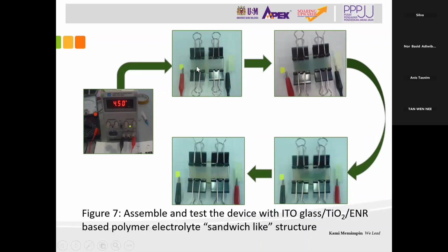This is a demonstration of an electrochromic device showing the polymer electrolyte in the operating mode. You can see here the device changes from transparent to dark blue color. The device is applied with a low voltage of 4.5 volts, and this process takes about 1 to 2 minutes to obtain a dark blue color. After that, it will become transparent again.